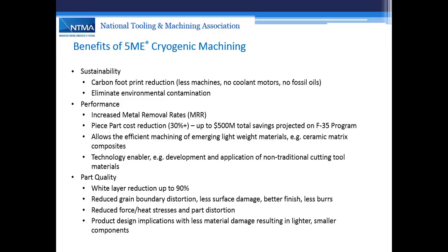From a performance perspective, there are metal removal rate increases. There was one very significant landmark study that we did with Lockheed Martin on aerostructure components, where we were able to reduce their piece part cost by up to 30% from billet to flight part. It was announced by Lockheed management that there's a possible $300 to $500 million in projected savings on the JSF program with these types of cycle times and cryogenic machining. It will also allow efficient machining of emerging lightweight materials.